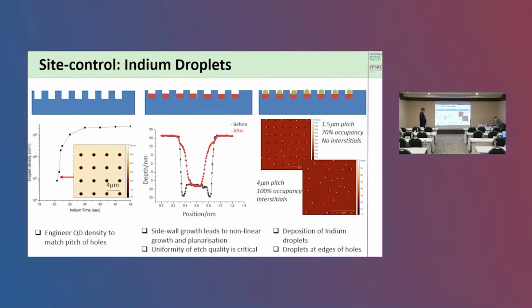And finally, when we supply the indium, then indeed we do see that the indium forms in the holes, and that this happens at different pitches. In the case of 1.5 micron pitch, we actually have good statistics. We've got about 70% occupancy. In other words, 70% of the holes have a droplet in them, and we get no interstitials. In other words, we get no droplets in between these holes. Okay, so that's not bad.